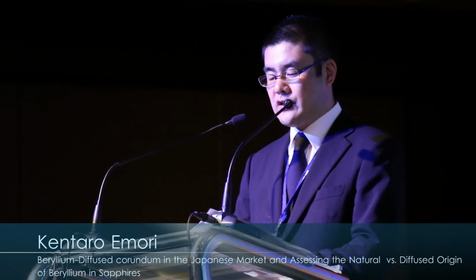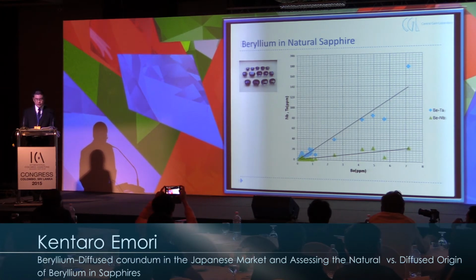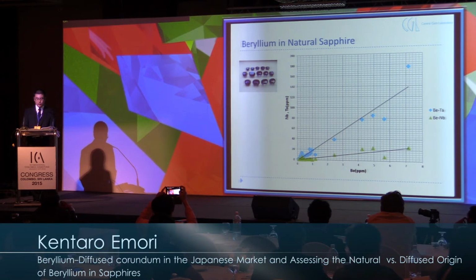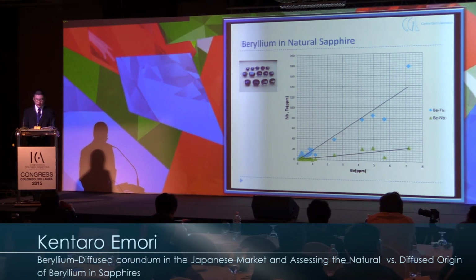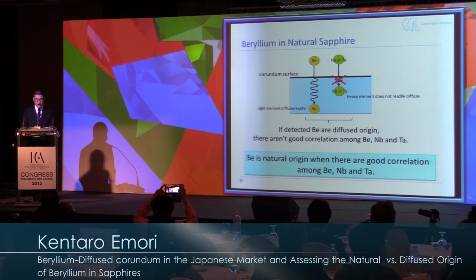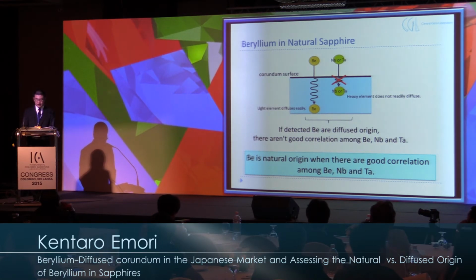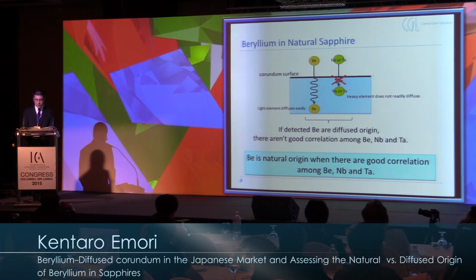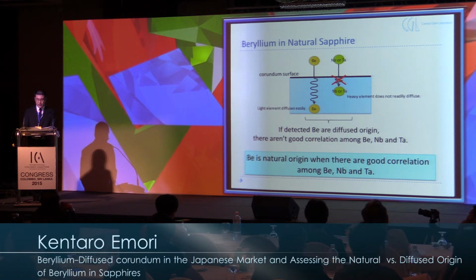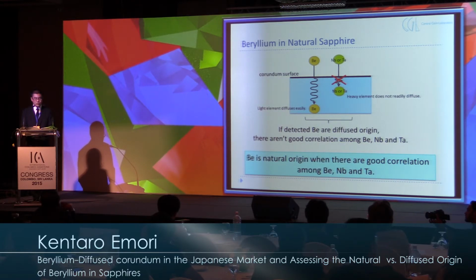I examined the correlation between beryllium, niobium, and tantalum. The blue squares show the concentration of beryllium and tantalum, and the green triangles show beryllium and niobium. After plotting, there is a good correlation among them. Because beryllium is a light element, it diffuses into corundum by heating. But heavy elements such as niobium and tantalum cannot diffuse. Therefore, if these elements were diffused at the same time, we could not recognize a good correlation among them. If there is a good correlation among beryllium, niobium, and tantalum, this beryllium is of natural origin and has existed in the corundum crystal since birth.